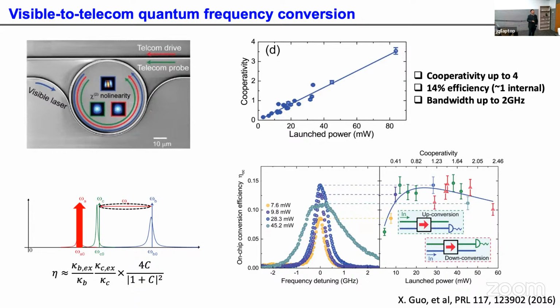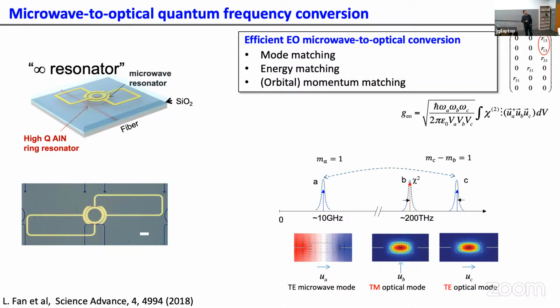Okay, so that was the optical to optical conversion, and a similar device inspired us to do microwave to optical conversion. The device is a little bit different. It's the same kind of ring resonator, made of polycrystalline aluminum nitride. And to support the microwave mode, we produce this microwave ring resonator here. Clearly the phase matching is quite different. In our geometry, we cannot use the previous D33 element of the Chi2 tensor, because we would like the microwave field in plane so we can have a stronger microwave field. So the nonlinear element that we're using in this Chi2 tensor is the R13 element.